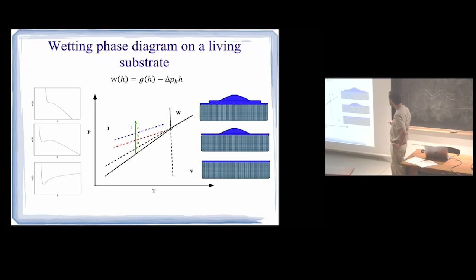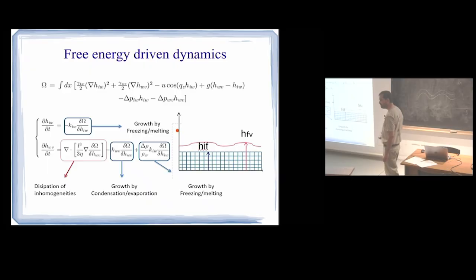And eventually, if delta P is sufficiently large, then this negative slope line is so large that my minimum vanishes and I get instabilities. And I get the instabilities observed in experiment. So I think this explains the experimental observations. Just to tell you very briefly, this theory is the plain and simple theory that can be done just from bare thermodynamics and little out-of-equilibrium concepts.